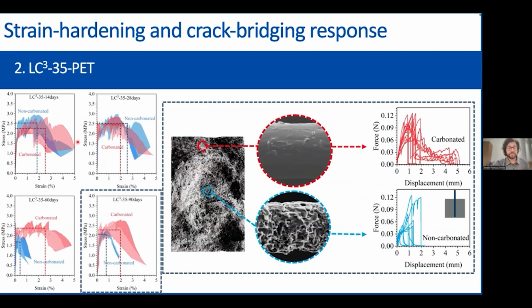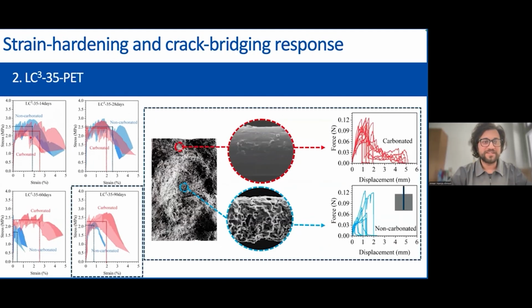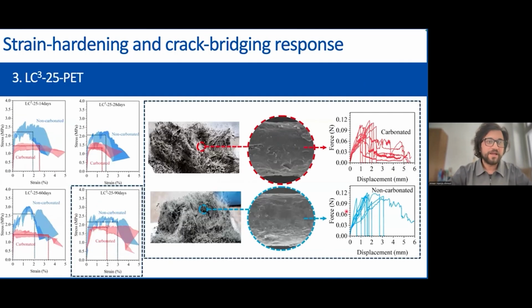This is the result of LC3-35. Because this matrix is inherently less alkaline, you see the degradation is also slower. But still, the blue, non-carbonated samples still degrade, while the carbonated samples preserve the whole response. And this is also visible in the single fiber pull-out test. And lastly, I will show you the LC3-25. As I mentioned earlier, the alkalinity levels are naturally so low that you see the blue curves, which are non-carbonated, preserve a very good strain hardening response. In this case, we don't need to carbonate, because carbonation, as you've seen, reduces the compressive strength, opens up the microstructure, and leads to more weakening of the microstructure. So here, carbonation is actually detrimental to the mechanical properties. So in this case, we don't need to carbonate for accelerated aging. For prolonged aging, the normal hydrated LC3-25 shows sufficiently good strain hardening performance.